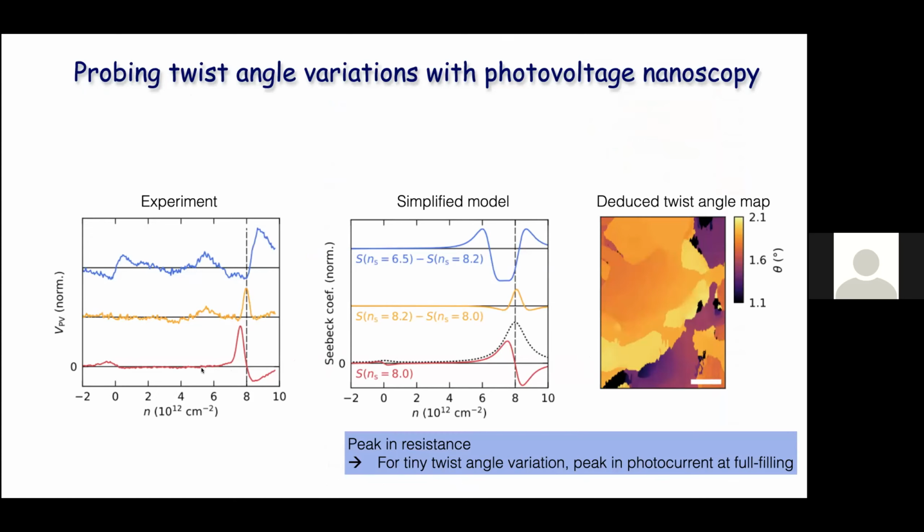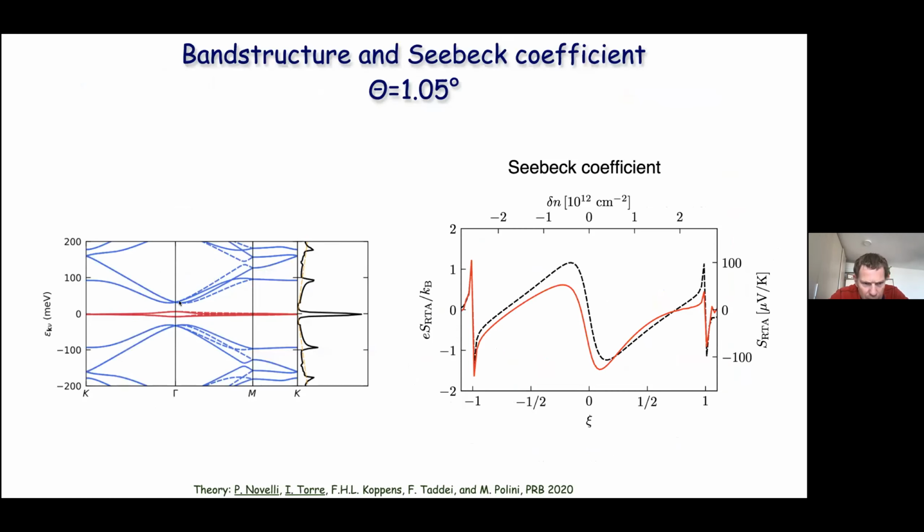Okay. As expected. Yeah, because these flat bands have a bandwidth of just a couple of milli-electron volts, right? So when you are at room temperature, this effect is completely smeared out. The way you can also see it is that here you have a gap, right? So basically this is the fact that you're entering a gap. This gap is shown here in the band structures, this gap here. And this gap is on the order of 5 to 10 milli-electron volts. So at room temperature, you will not see that.